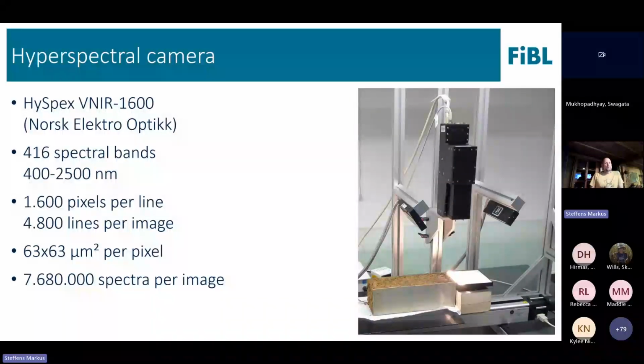And for these cores, which we took, so 30 centimeters long and 10 centimeters wide, these were more than 7 million spectra or pixels per image. And what we did, so we took one picture, then we sampled some interesting spots, we planished the surface again and took the next one. So in this case, that was the very first core which we took. We took 7 images. So in the end, we got not a full volume, but we had 30 centimeters long, 10 centimeter wide, 10 centimeter deep. And for this one, we had 7 images.